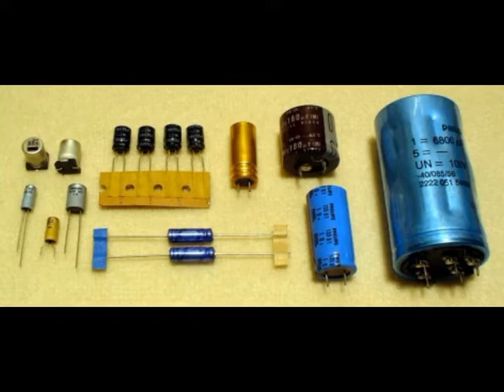The value at a measuring frequency of 1 kHz is about 10% less than the 100/120 Hz value. Therefore, the capacitance values of electrolytic capacitors are not directly comparable and differ from those of film capacitors or ceramic capacitors, whose capacitance is measured at 1 kHz or higher. Measured with an AC measuring method with 100/120 Hz, the measured capacitance value is the closest value to the electrical charge stored in the capacitor. The stored charge is measured with a special discharge method and is called DC capacitance. The DC capacitance is about 10% higher than the 100/120 Hz AC capacitance. The DC capacitance is of interest for discharge applications like photoflash.